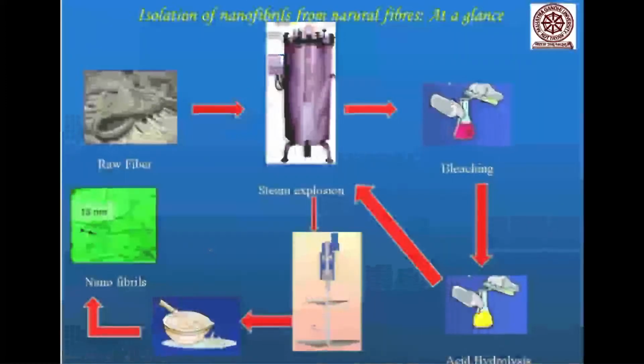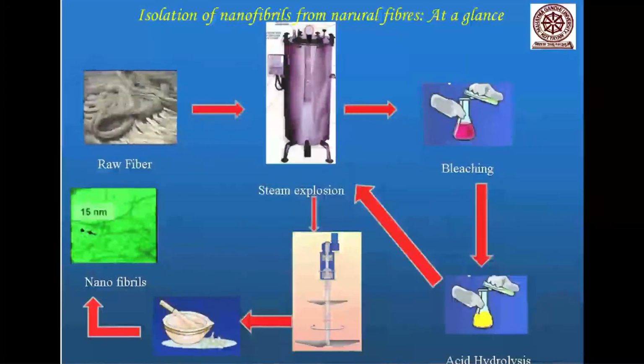So you can see the nanocrystals made by Mohammed's group from wood flour. Look at these nanocrystals, short nanocrystals. Now I will show you the plant we have in the campus. You see, this is the raw fiber we collect. We chop them into smaller length, put into a steam explosion unit, high pressure and temperature, go for a bleaching, acid hydrolysis, then high pressure homogenization process. We repeat the process till we get nano.